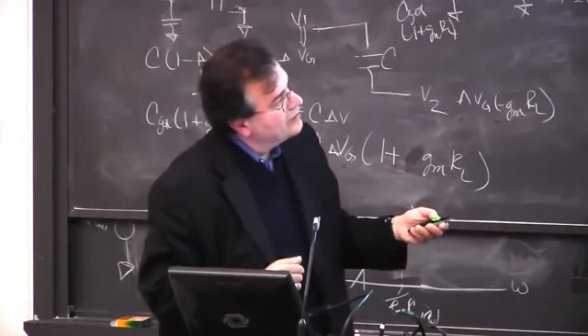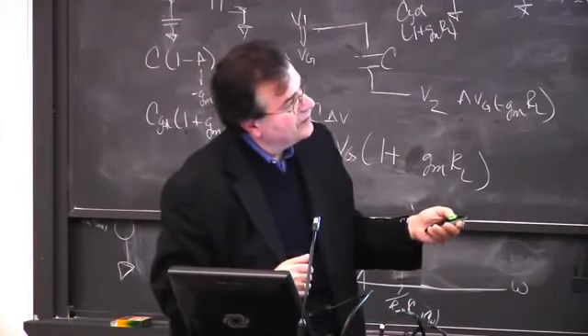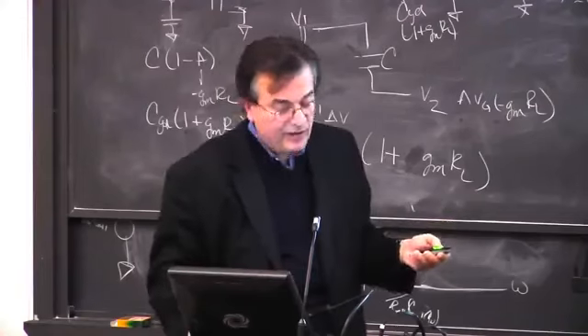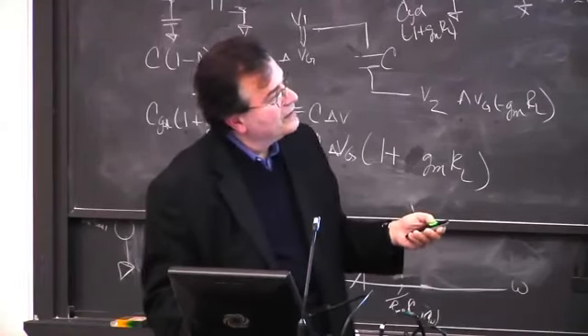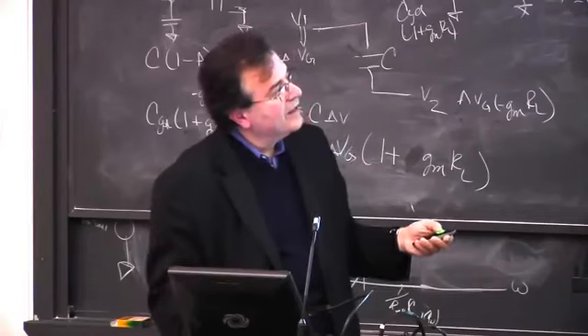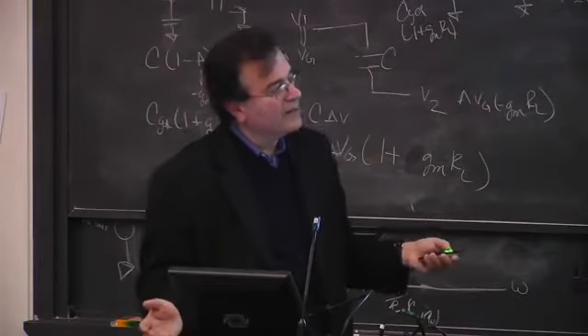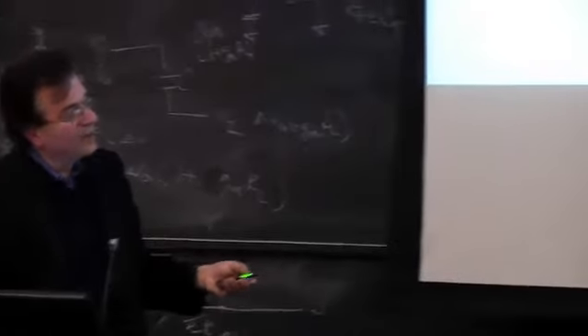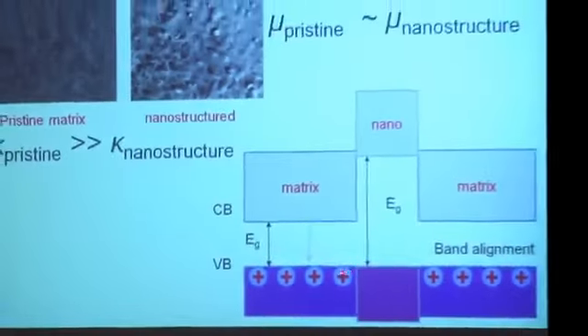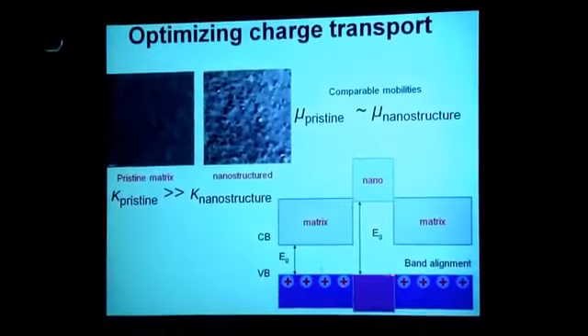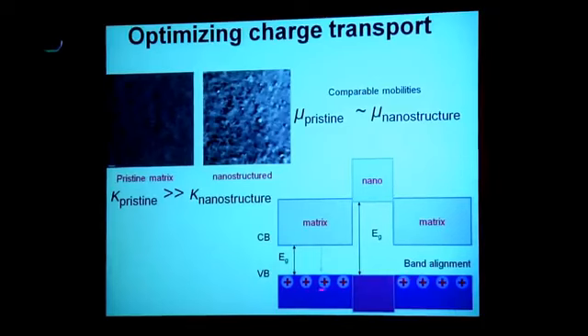And so if you have holes, they can transport through the material. They can find states across the material as well. Plus, the high mobilities give long mean-free paths. And these nanodots are, as I said, between 1 nanometer and 15 nanometers. So there's always states to go through, and also they're small enough that electrons can pass along easily. So if you're a hole, you may not notice that there is a second phase here because you find the right states to come across.